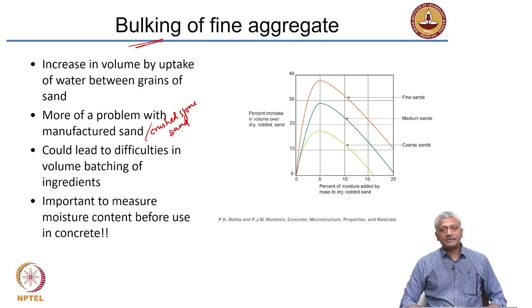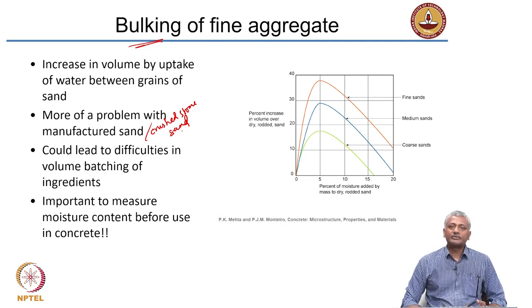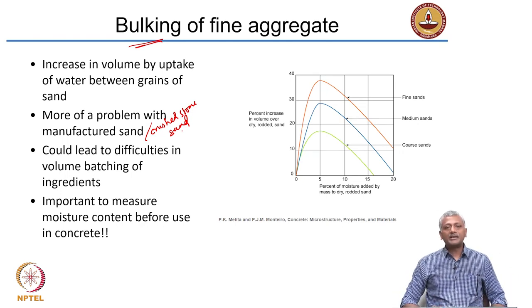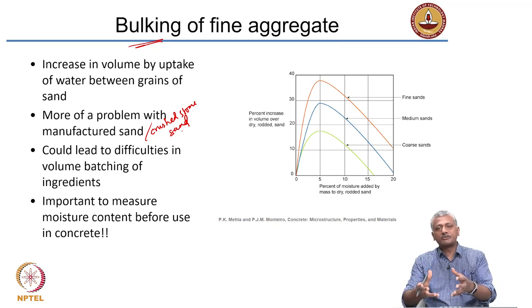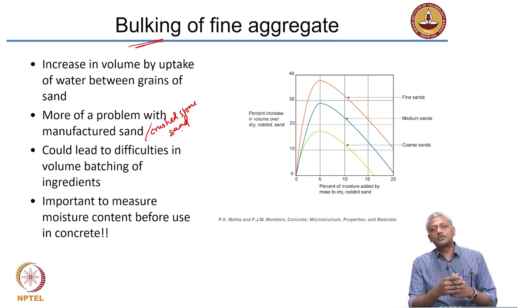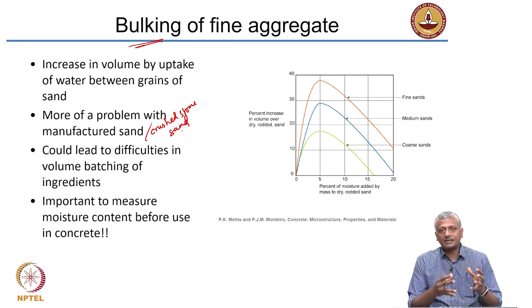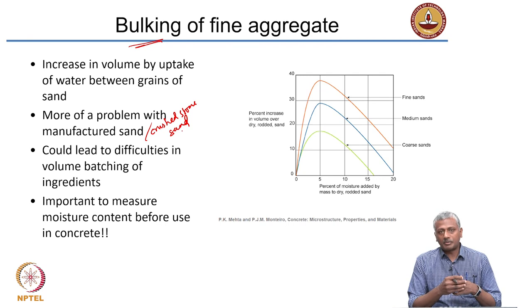This is truly a big problem only in the case of concrete where you do volume batching — meaning you are measuring quantities by volume. If you are measuring by mass, all you have to do is dry this mass of wet sand and determine how much water is actually inside. That way you can get the exact mass of dry sand and the mass of water properly input into your concrete mix. If you are checking volume, then you have a problem.